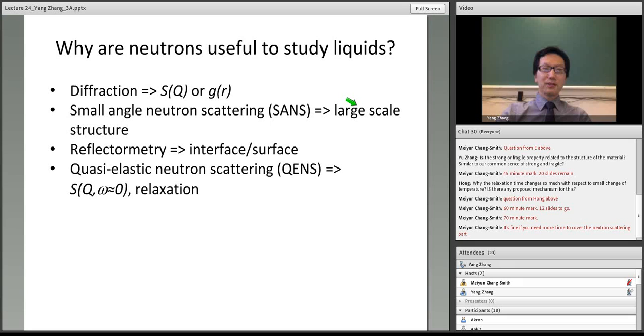And more importantly, with neutrons, we can do inelastic measurements. With other techniques like X-rays, we can do photon correlation spectroscopy, which will be similar to quasi-elastic neutron scattering, but for X-rays, the Q range and the time range are very different from neutrons. Neutrons are very natural to study dynamics because neutrons have energy very similar to the fundamental excitations of the materials. So it's much easier to detect such energy transfer with neutrons.